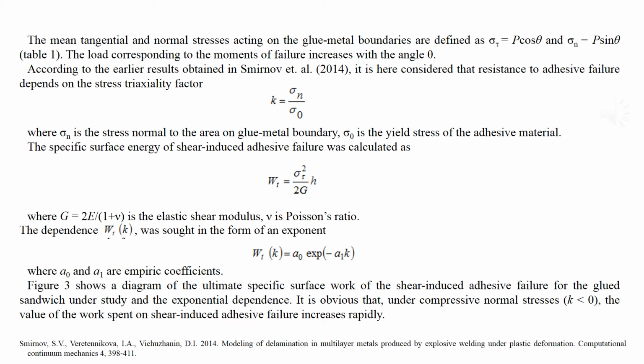The dependence of specific surface energy on the stress factor was described in the form of an exponent, with A0 and A1 empirical coefficients. Figure 3 shows a diagram of ultimate specific surface work of shear-induced adhesive failure for the glue sandwich under study and the exponential dependence. It is obvious that under compressive normal stress, when the stress triaxiality factor is less than 0, the work spent on shear-induced adhesive failure increases rapidly.